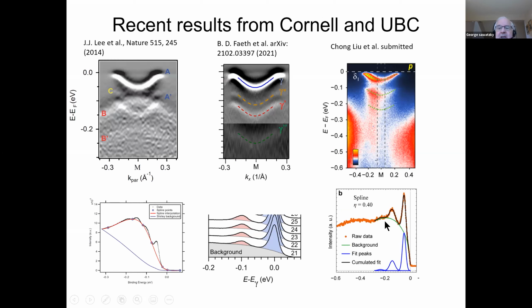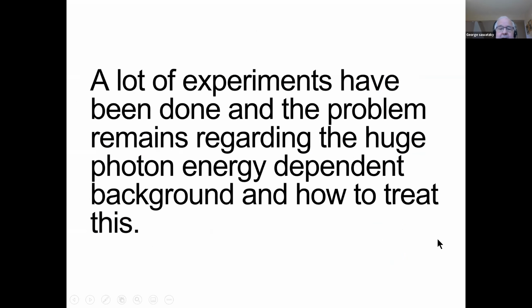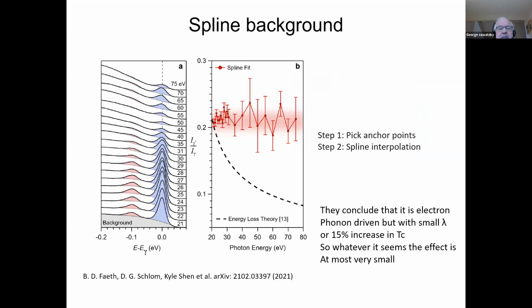If you look at this spectrum here on the right at the bottom, you have this very huge background here, and you don't know what the shape of it is inside here. So it's very difficult to say what the relative intensities of these peaks are. But there's a very recent experiment, and there are a lot of experiments, from Z.-X. Shen's group, and Stanford and in Berkeley, they've tried very hard also. We have also, but we simply couldn't make much sense of it. But here's a paper that just recently came out with D. G. Schlom, and Kyle Shen and so on. These are very reliable results and very nice experimental results indeed.